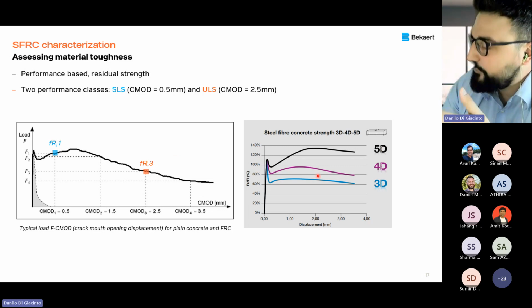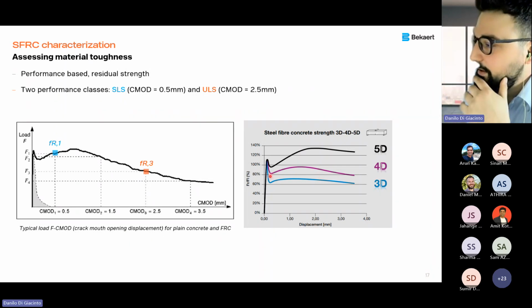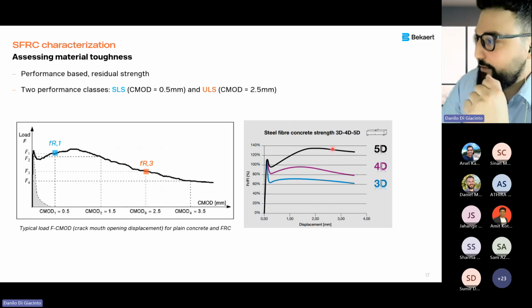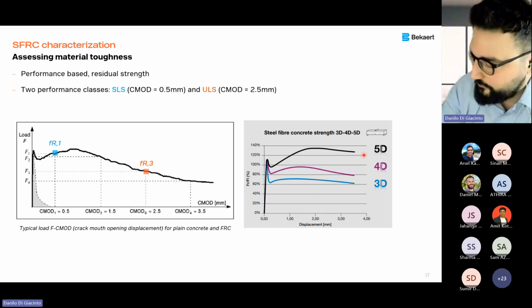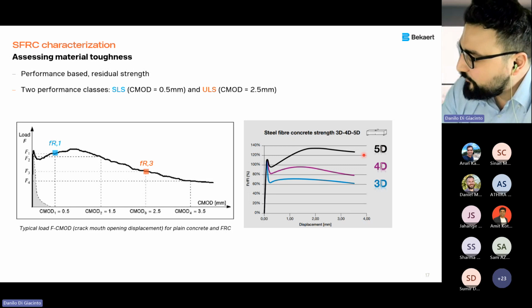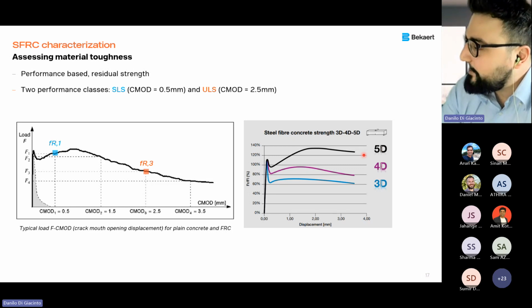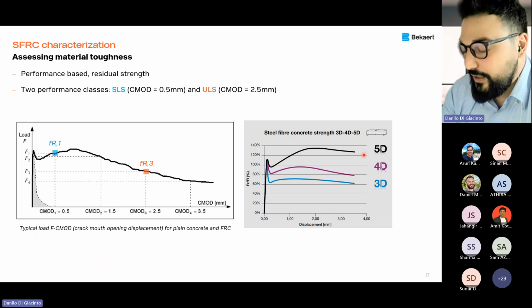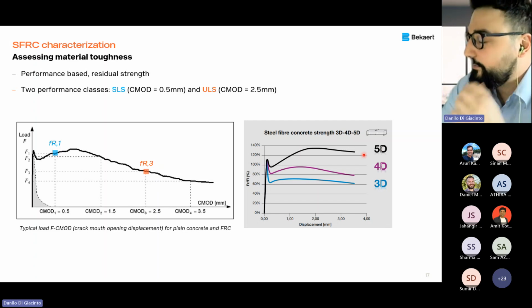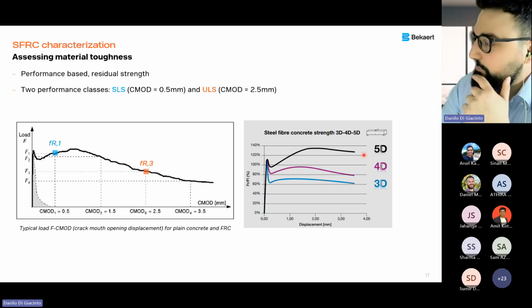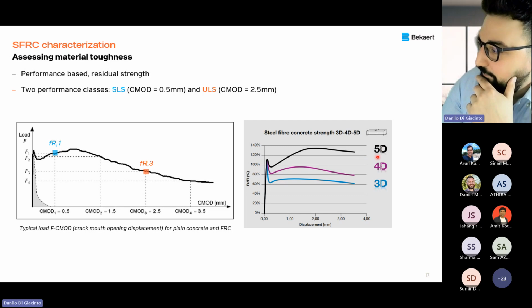Steel fiber reinforced concrete, according to the dosage, the steel fiber type, and the base concrete strength, can have different behavior. It can be softening, it can be hardening, and it depends on the fiber performance. The more advanced the fiber, the more advanced the hooking and anchoring mechanism. The stronger the tensile wire strength, the better the performance within the concrete. With the 5D and 4D, you can also have structural applications with fiber-only reinforcement.